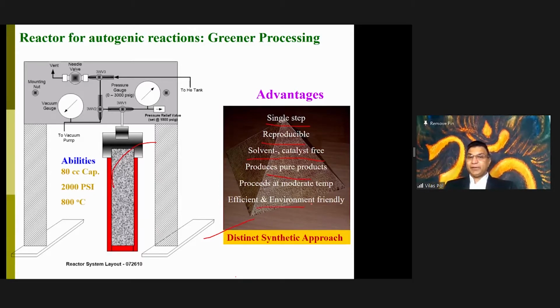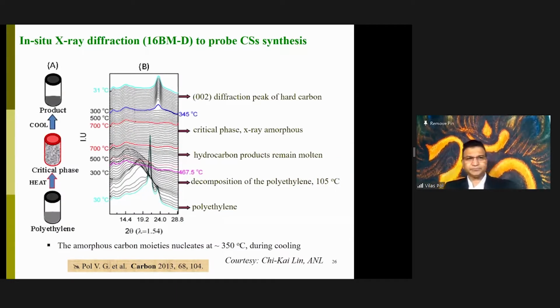We keep it environmentally benign because we do not release anything to the atmosphere. Everything is sealed and controlled, as you can see in this developed reactor. So there are advantages to using this process versus all others. This reactor can hold up to 2000 PSI pressure. So this material is grown under the pressure. The reactor could hold up to 800 degrees Celsius temperature, and the size of the reactor was 80 cubic centimeters.